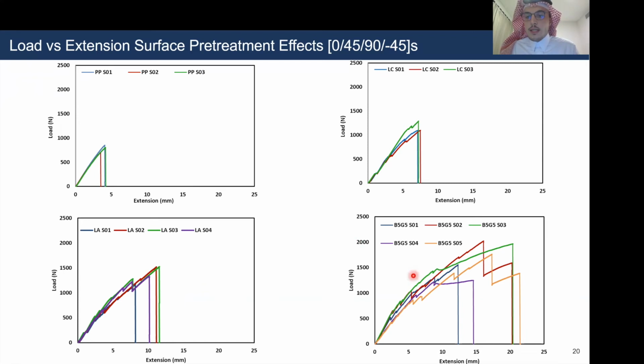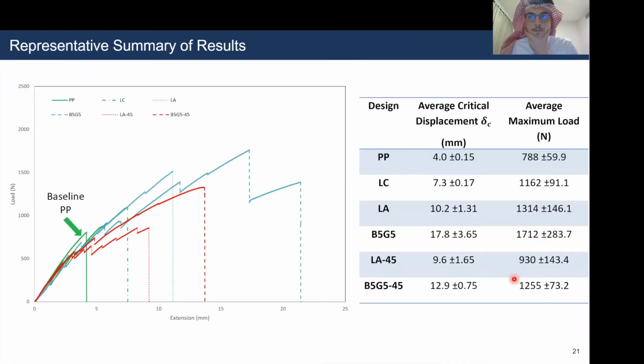And we noticed that the failure started transforming into progressive failure rather than having catastrophic sudden failure with the PP. And to notice how the T-joints would change when we change the surface fiber direction, we can analyze the results by looking at how, for example, a 0-degree patterning can compare with a 45-degree patterning. We can see that the area under this curve is almost doubled when it was switched from 45 to 0.